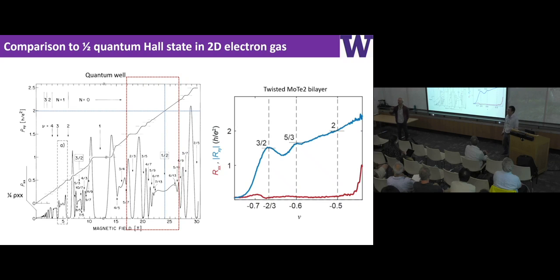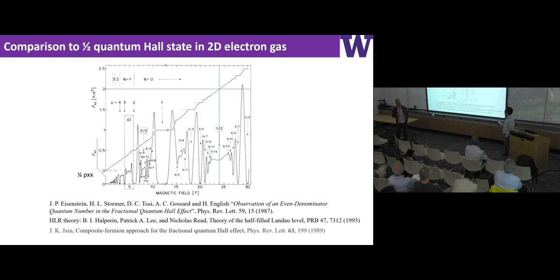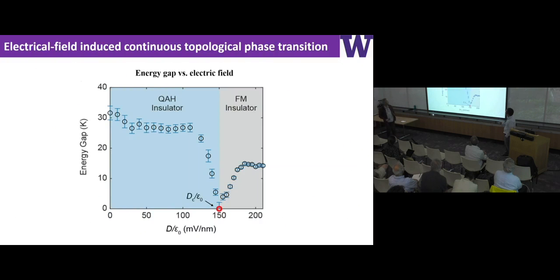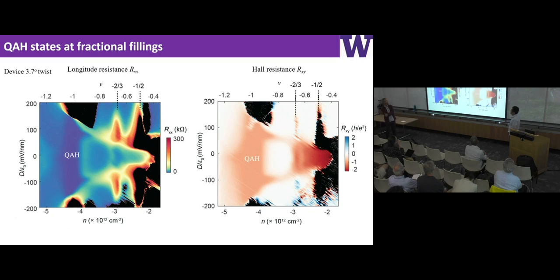We had another question back there. This is very exciting. I noticed that in your MCD, in the range from 2/3 to 1, there's a lot of MCD signal. From the transport measurement, RXY is almost zero. Excellent question. So the question is that in my MCD measurements, magnetic circular dichroism, there are ferromagnetic states across this phase space. But in my transport, RXY looks very small in this regime. The question is why MCD shows a strong signal but RXY is small.